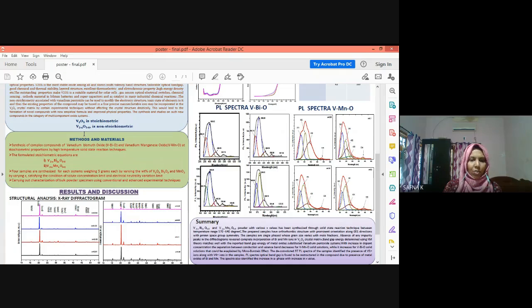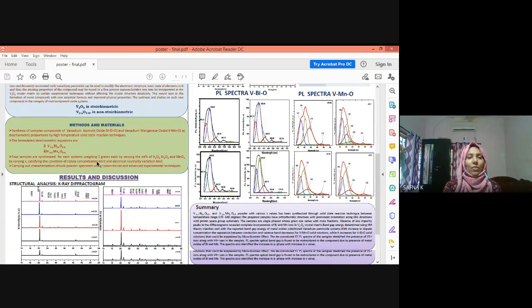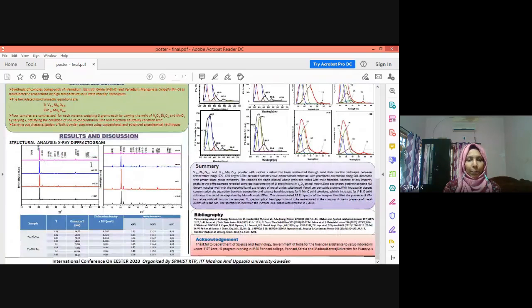Here, we synthesized VBIO and VMNO complex compounds by the solid-state reaction technique in the temperature range 570 to 640 degrees Celsius and carried out different characterizations such as XRD, UV-visible spectra, and photoluminescence. And this is the XRD pattern of the prepared samples for different mole concentrations. This is for the VBIO system and this is for the VMNO system.